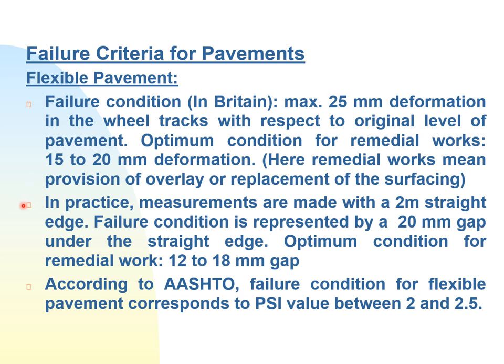In practice, measurements are made with a 2 meter straight edge. Failure condition is represented by a 20 millimeter gap under the straight edge. Optimum condition for remedial work, 12 to 18 millimeter gap. According to AASHTO, failure condition for flexible pavement corresponds to a PSI value between 2 and 2.5.